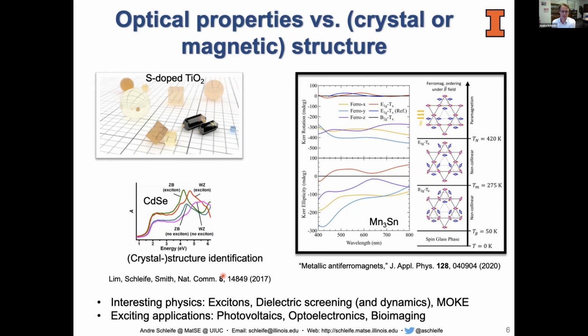It depends very much on whether the light is propagating perpendicular or parallel. Right. So we have access to this information through the dielectric tensor. The way we compute this, I can tell you at least, is we calculate the full dielectric tensor, so all diagonal as well as off-diagonal components, and then that, relative to the orientation of your field, tells you about the anisotropy. So even if it's not in this figure, we do have access to that data.